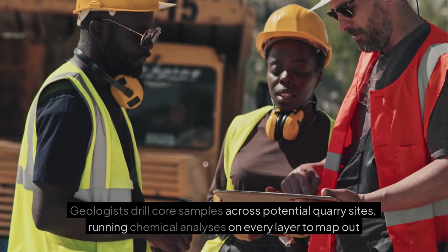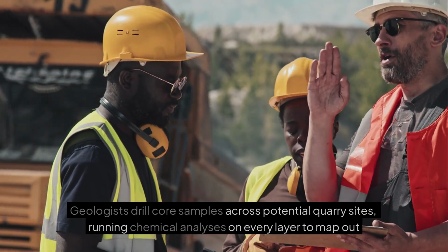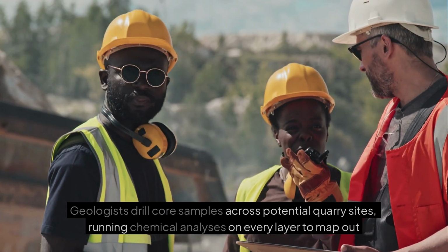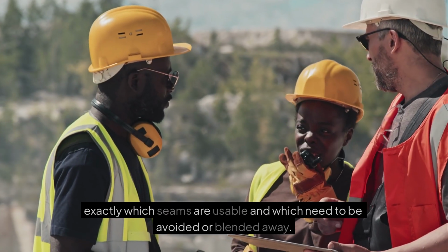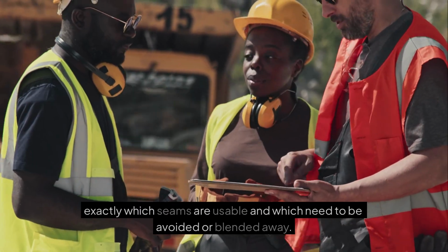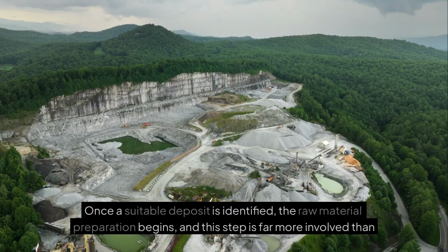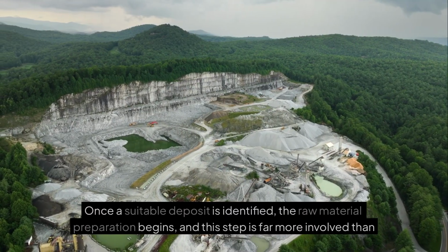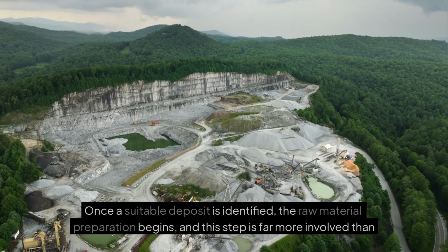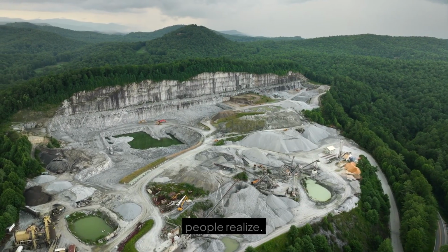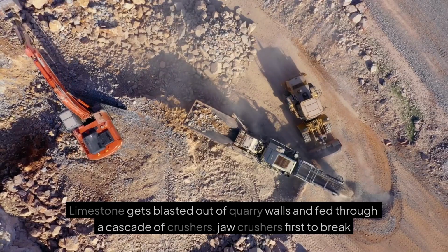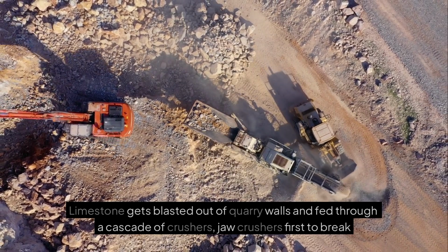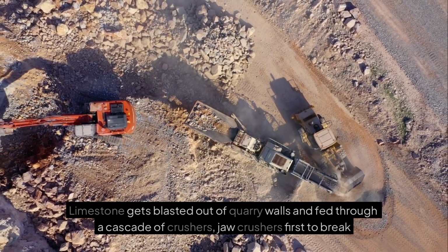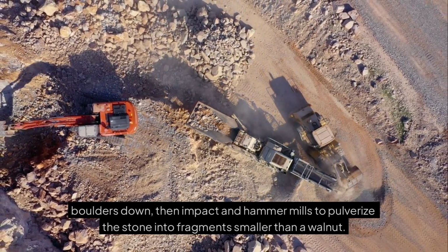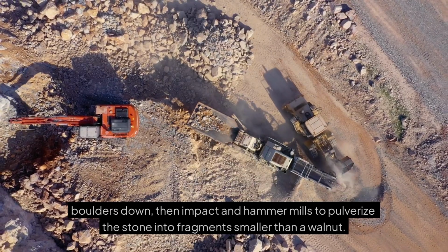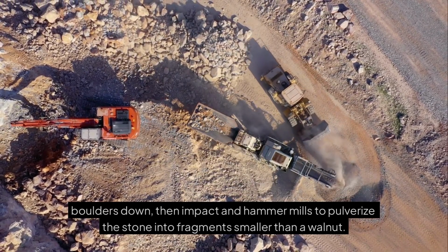Geologists drill core samples across potential quarry sites, running chemical analyses on every layer to map out exactly which seams are usable and which need to be avoided or blended away. Once a suitable deposit is identified, the raw material preparation begins, and this step is far more involved than people realize. Limestone gets blasted out of quarry walls and fed through a cascade of crushers, jaw crushers first to break boulders down, then impact and hammer mills to pulverize the stone into fragments smaller than a walnut.